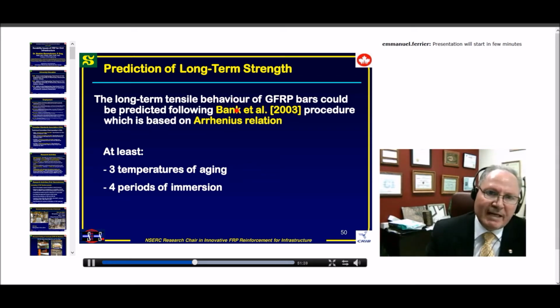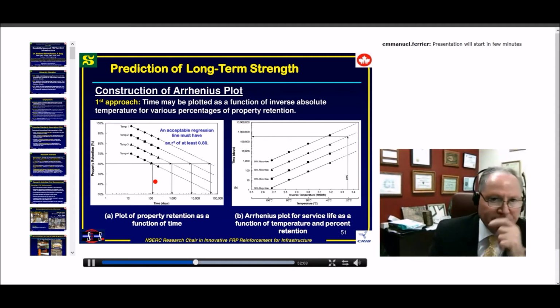And here I am reporting one procedure developed by Larry Bank in 2003, which needs 3 temperatures of aging and 4 periods of immersion. So here it could be like 20 ambient, 40, and 60, and here it could be 4 periods of immersion, like 45 days, 3 months, 6 months, and 1 year, as an example. Or 1,000 hours, 3,000 hours, 5,000 hours, and 7,000 hours, something like that. And from this, this is from Larry Bank, we can draw that kind of curves.